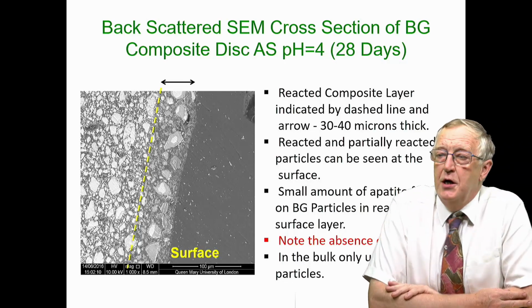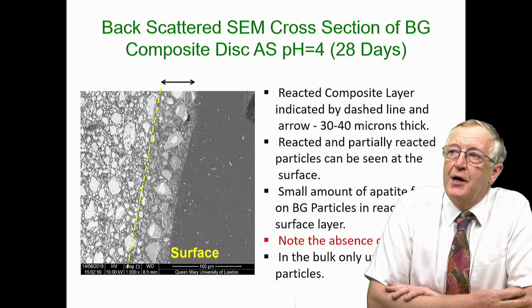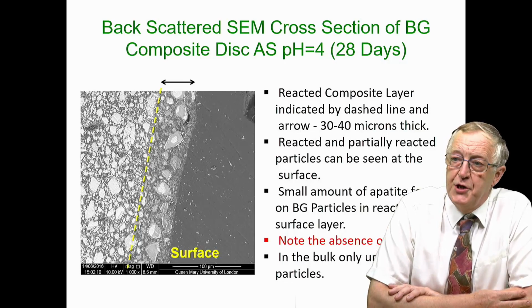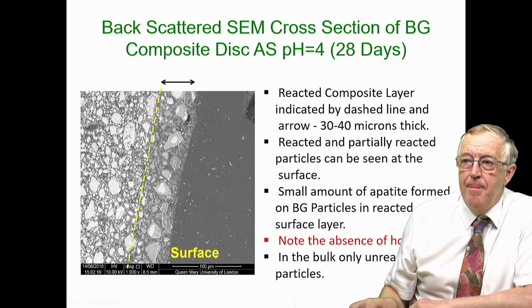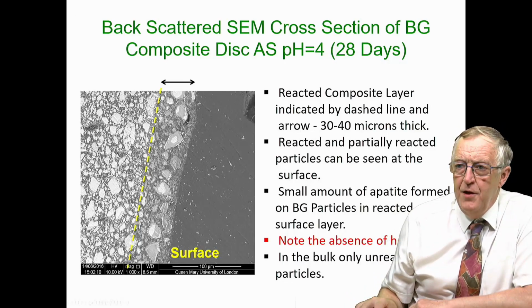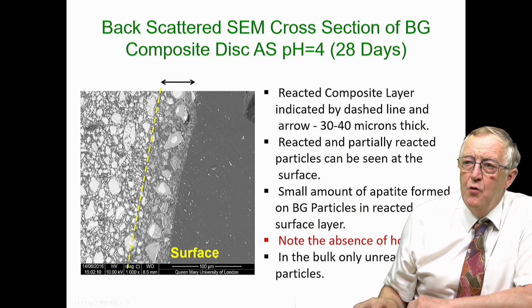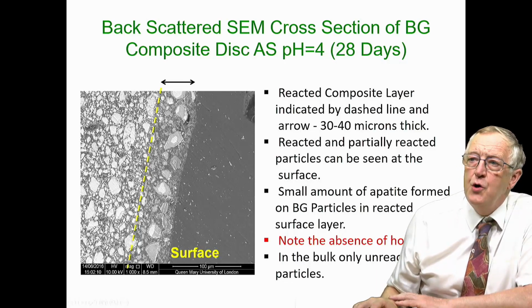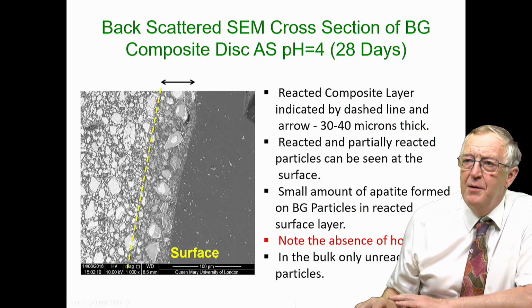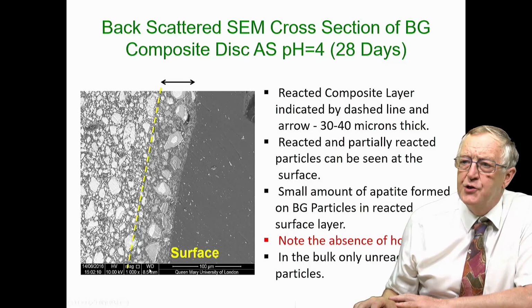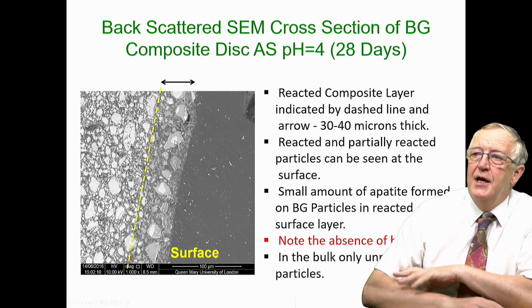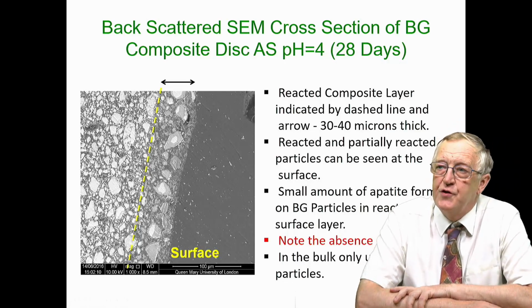This slide shows a backscattered scanning electron micrograph of a cross-section of a bioglass composite. You can see the bioglass particles in the resin matrix here. But if you look over to the right of the dashed yellow line, you can see the particles have degraded. There's a change from being whiter to a darker grey, and you can see this one's reacted almost completely, whereas this one here, the centre hasn't yet reacted. And this is after the disc has been immersed in artificial saliva pH 4.